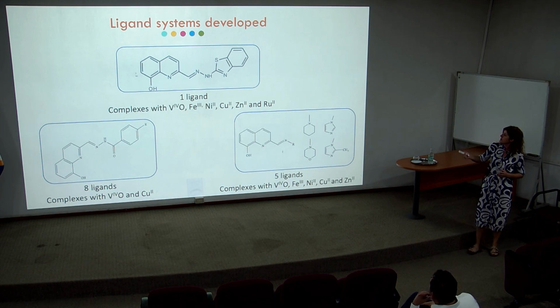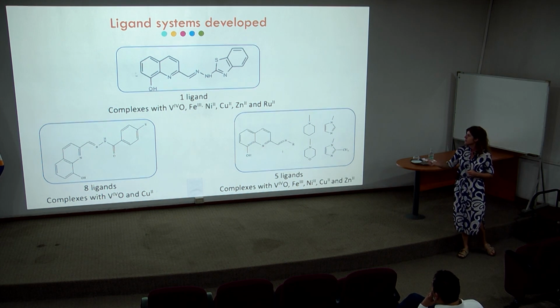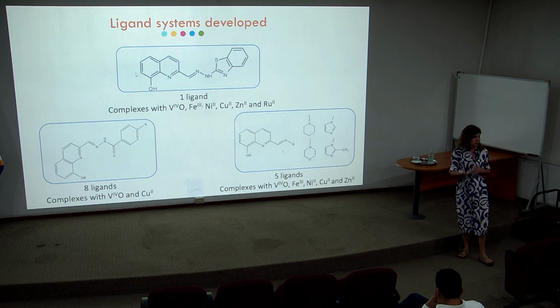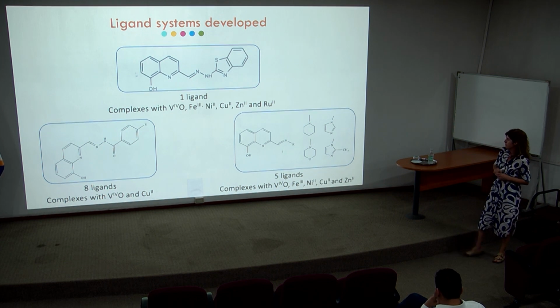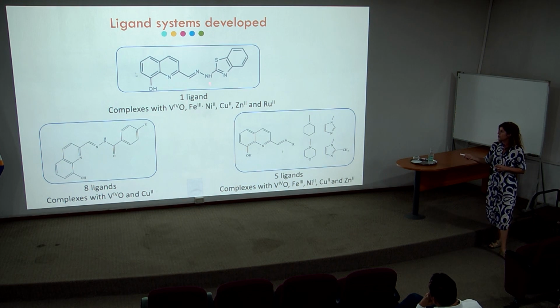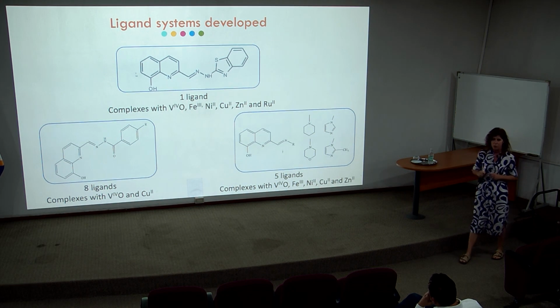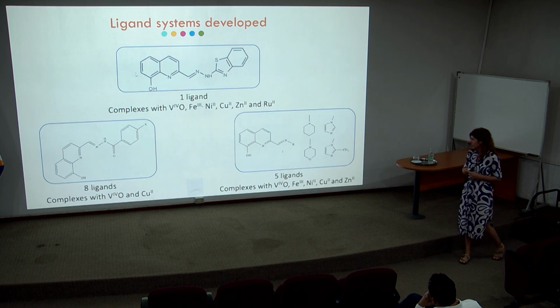3 different systems, one in which we synthesized one ligand and complexed it to a series of metal ions, vanadium-4, iron-3, nickel, copper, zinc, and ruthenium, although I'm going to focus on the zinc data that we obtained.